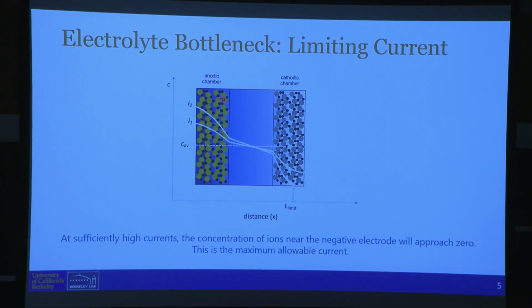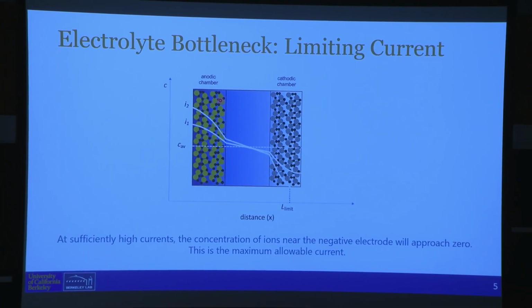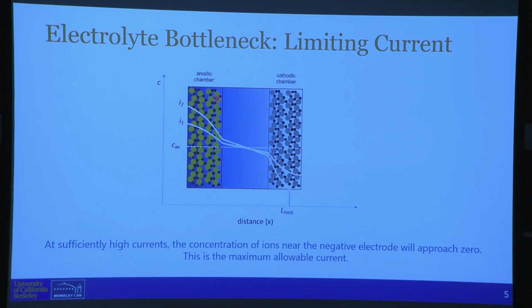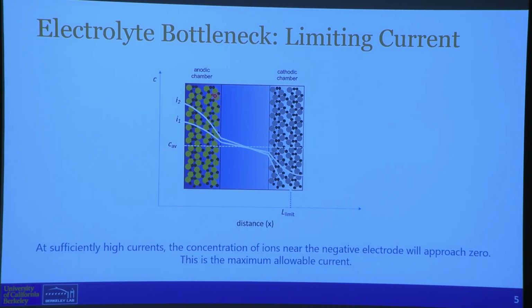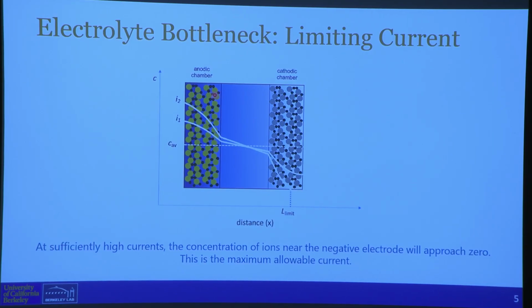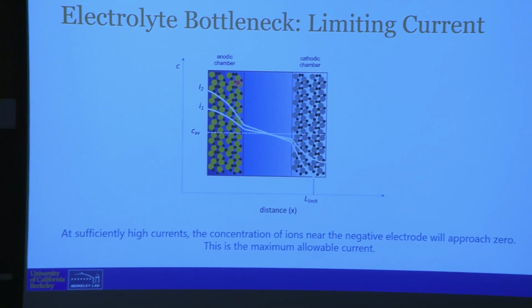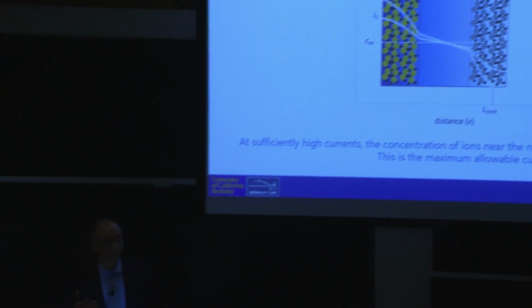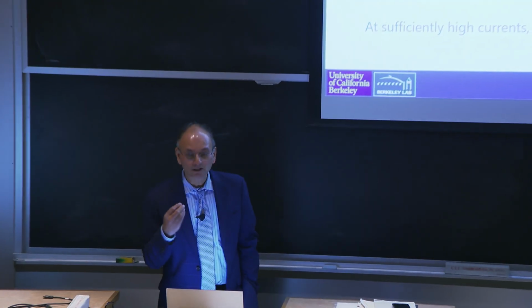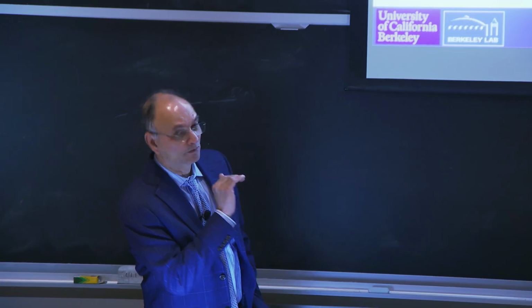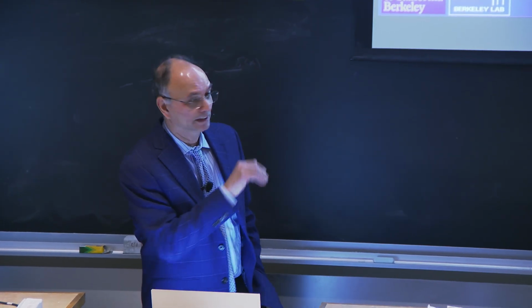There is also a recognition of why an electrolyte can serve as a bottleneck. You see, you have 2 electrodes, and the lithium shuttles between particles shown on your left and right, and lithium enters the electrolytic phase in the middle through one electrode and then goes out the other. And as a result of that, this electrolyte develops salt concentration gradients. The electrolyte you carry in your pocket is a mixture of a salt and an organic solvent. And the salt tends to accumulate on one side from where the lithium ions are getting in, and then exits the other side. Okay.